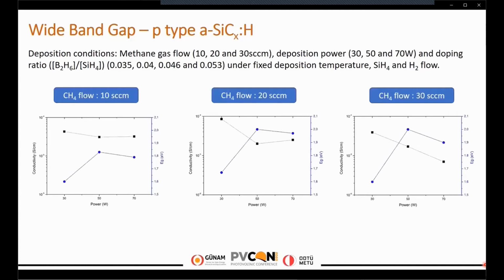I would like to show you conductivity and band gap results of various methane flow and deposition power. The black square results belong to conductivity and the blue circles show the band gap results. Starting from 10 SCCM to 30 SCCM, for conductivity results, the general trend is decreasing. The conductivity value decreases with increasing deposition power, and for band gap values, increasing deposition power leads to increasing band gap values.